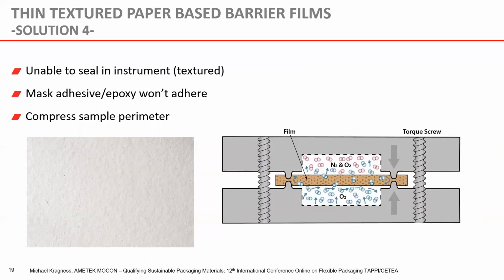Now, another solution that we use to test these types of structures is where we actually compress the microporosity, using a force to essentially remove the porosity from the material. You see in this diagram, we have a porous piece of paper, and then we have raised lips on both sides. These raised lips bite into the structure, and we have a compressive force that compresses the perimeter of the sample. This compresses it so much that it removes the microporosity, so it removes the edge diffusion. So it seals it off, so our atmosphere can no longer come into the structure.